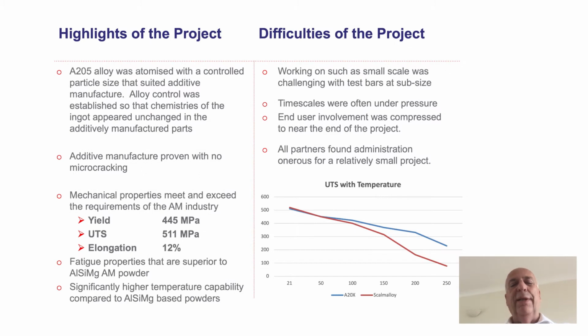So the highlights of the project. Now on the top right hand side, you'll see there are some of the difficulties. I don't intend spending any time on difficulties. There's always administration, there's always paperwork, but that's part of life. What we were really looking for, as I said before, is can we prevent microcracking? Any microcracks totally ruin it as an additive manufacturing material. And can we prove that the mechanical properties that we show in A205 cast material, which in fact is the world's strongest cast aluminium, can be translated or even improved upon in an additively manufactured powder made from that alloy.